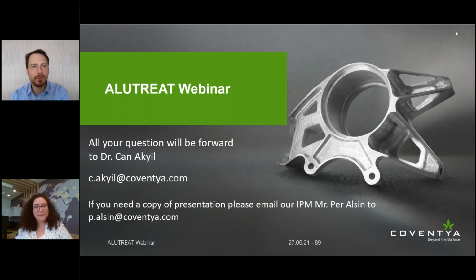Electrocoloring, we talked about the precipitation efficiency. Anodizing is a conversion process, so it is much more forgiving than the coloring. Therefore, when you're doing AC coloring or electrolytic coloring in your lab, the ratio of anode to cathode plus the distance in between them makes a huge difference. When you're doing a lab sample compared to a big architectural anodized line, the time almost goes 3 times faster. So this was our pilot line.